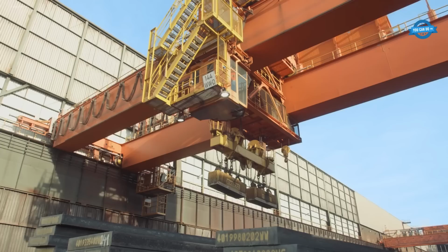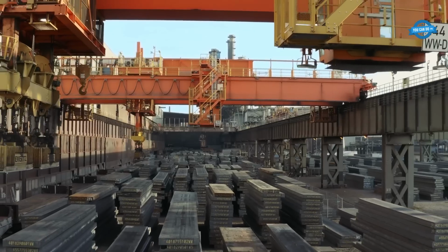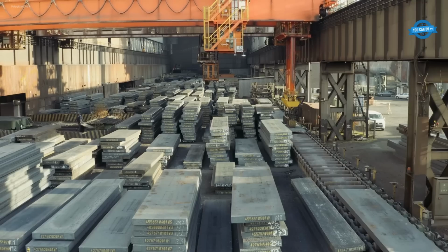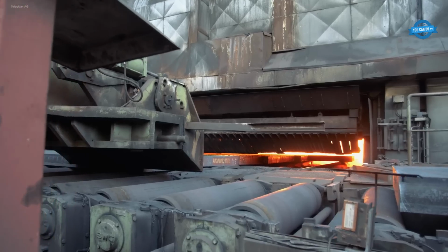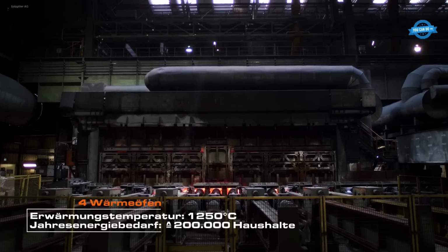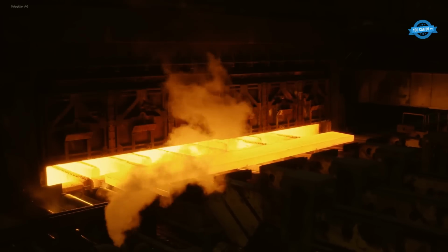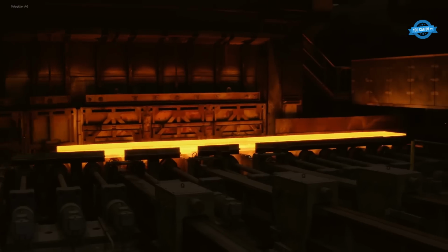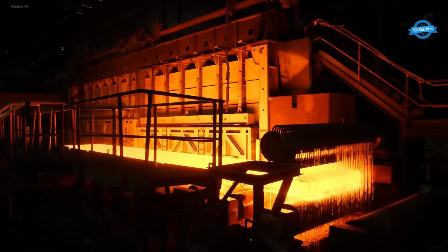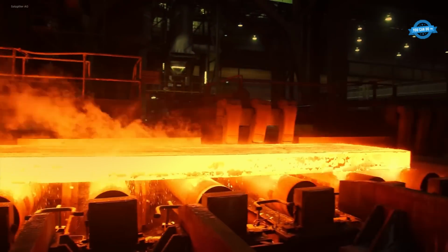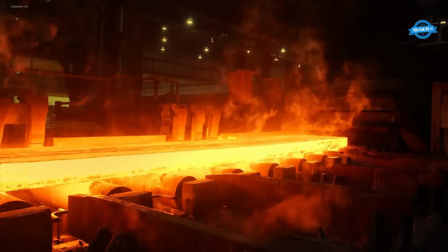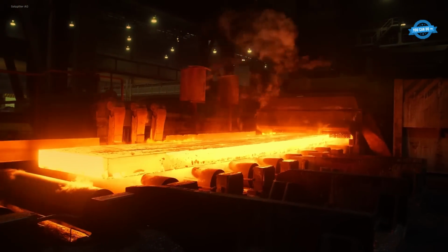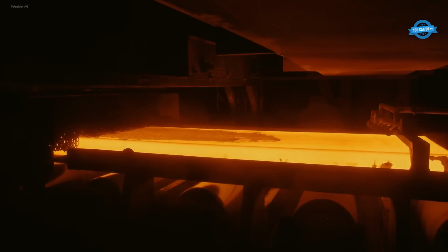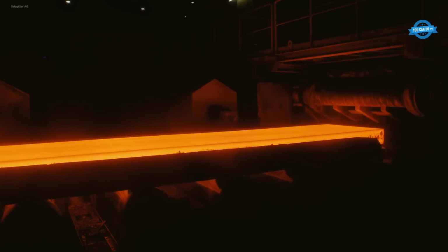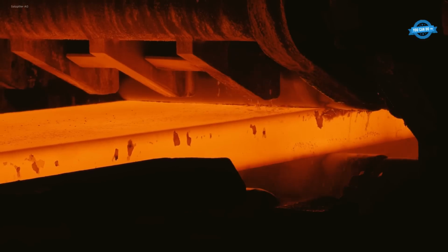At Salzgitter Flachstahl GmbH, the hot rolling mill transforms massive steel slabs into coils up to 1.5 kilometers long. Stored across 15,000 square meters, up to 2,500 slabs are reheated in 4 furnaces to 1,250 degrees Celsius, consuming energy comparable to 200,000 households annually. The slabs are compressed in a powerful descaling press with 2,200 tons of force, reducing their width by 300 millimeters.